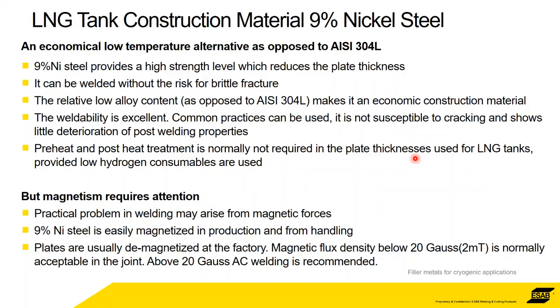So the idea of using the 9% nickel steel is it's an economical low temperature alternative compared to something like a 304L stainless. Because it's high strength, you can reduce the thickness of the walls in the tanks. It's got enough strength to support. 9% nickel can be welded without brittle fracture. It's a low alloy content, like we said, so it's economical compared to 304L, for example. It is readily weldable. It's not susceptible to cracking, and it shows little deterioration of post-welding properties.